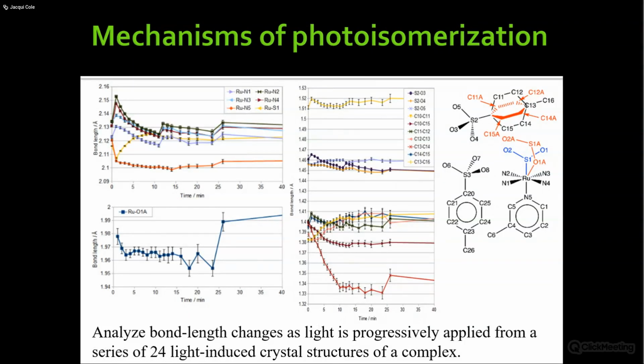So to try and really understand this, I plotted every single bond length as a function of time. This is a devil-in-the-detail type problem, looking for differences. This is really straightforward stuff, and this is what you see. In terms of the ruthenium's immediate surroundings, this is your ruthenium environment. The coordination does what you expect in some ways: bonds go down as others go up, and that makes sense because you're getting this metal-ligand charge transfer. But there's this strange jump at 11 minutes. That was a change in the mechanism I've just shown you. So something strange happens between 10 and 11 minutes, and also there's a bit of a jump at 26 minutes.